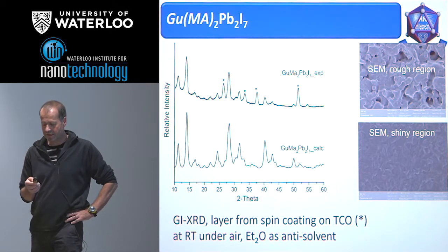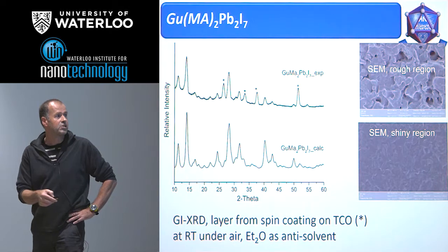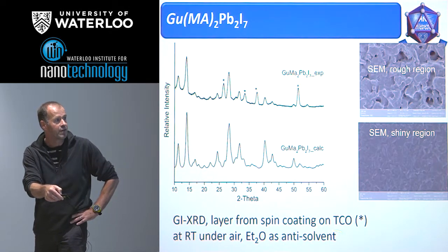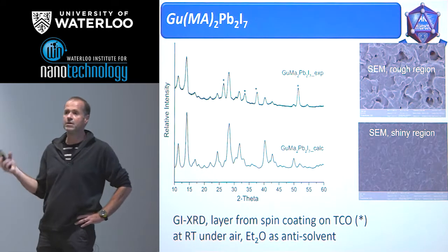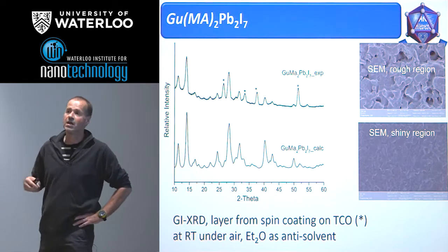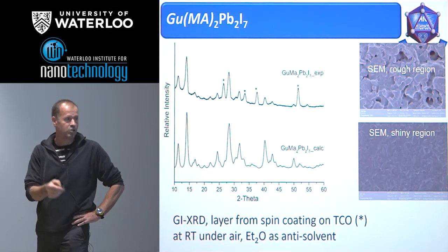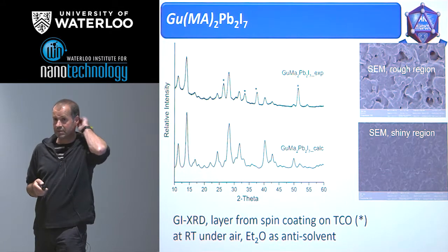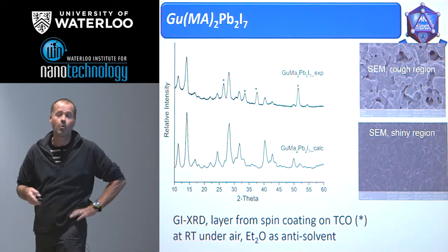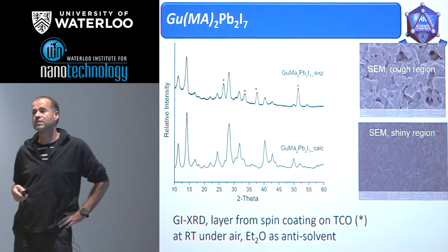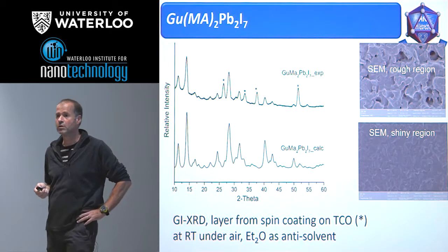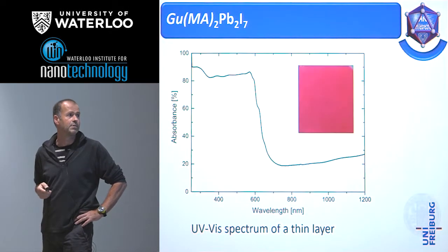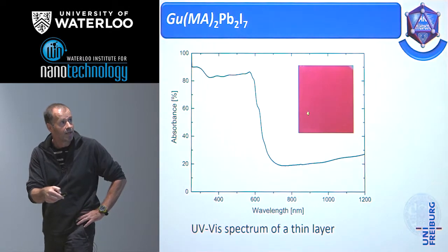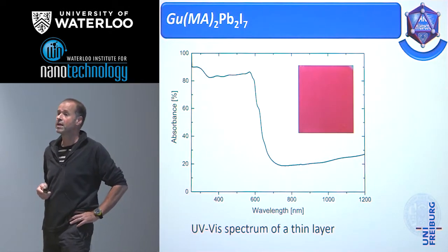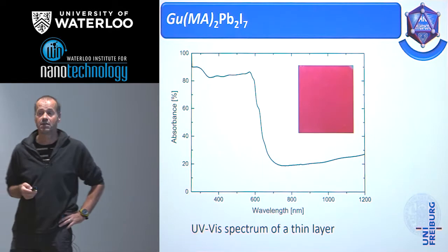And we did a formation of the layer by addition of ether as an anti-solvent. That means we dissolve it in an organic solvent like DMSO or something like that, and we precipitate it on the device by additional ether. And it's remarkable that it works already at room temperature. Normally you need 50 or 60 degrees Celsius to precipitate the methyl ammonium lead triiodide sample. We have a red shiny layer that corresponds nicely to the optical spectrum we have measured, so we can be sure that the active dye is indeed our compound and nothing else.